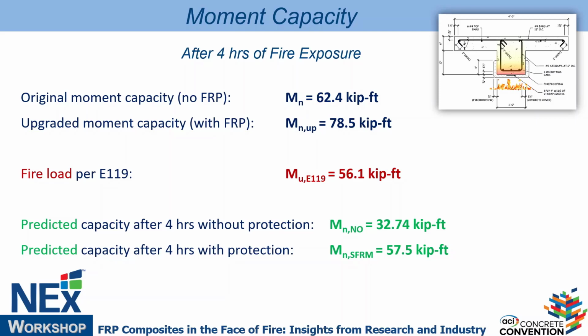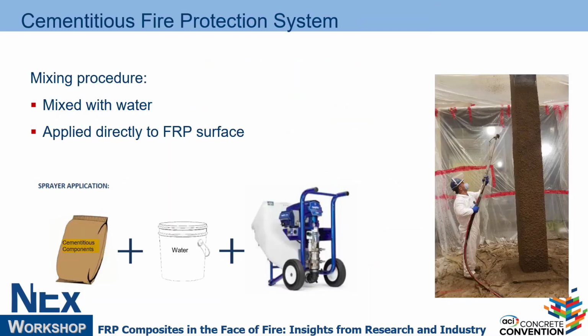So what happened is that after the capacity was predicted, without fire protection it is 32. With fire protection, by modeling, it is 57, right? And the load was 56. So it says, okay, that means it would last 4 hours theoretically, right? And it did. It did last for 4 hours without failure. Now, we don't know how far, because somebody mentioned it's very expensive to do the UL test. It is very expensive. Every minute costs a lot of money because of the amount of fuel. Once we reach 4 hours, it gets stopped. It could have lasted more, 5 hours, 6 hours, or it could be just 1 minute after 4 hours. We don't know. But it passed. So the theory does work, right? Every time we apply it.